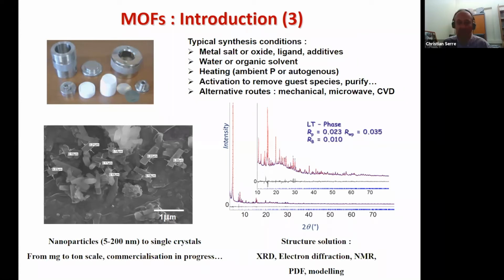Often people report, I've made a MOF by mechanical synthesis with a good yield, but the purity is not the same as the one made by batch. So this is something very critical for some applications, especially separation.